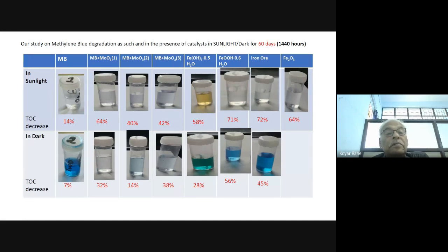Similarly, the molybdenum oxide prepared by a different method shows only 40%. It means the catalyst also makes a lot of difference in degrading the organic matter. When I use another molybdenum oxide prepared by some other method, it removes almost 42% of the organic. It means not only the catalyst, the preparation of the catalyst is also very important while dealing with the degradation of any organic matter. Here in this case, I have used only the methylene blue.